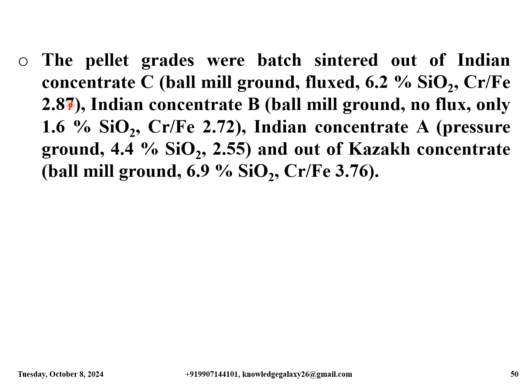The pellet grades were batch sintered out of Indian concentrates: Indian concentrate C, ball mill ground, fluxed, 6.2% SiO2, Cr/Fe ratio 2.87; Indian concentrate B, ball mill ground, no flux, only 1.6% SiO2 and Cr/Fe ratio of 2.72; and next, Indian concentrate A, pressure ground, 4.4% SiO2 and 2.55 Cr/Fe ratio. And out of Kazakh concentrate, ball mill ground, 6.9% SiO2 and Cr/Fe ratio of 3.76.